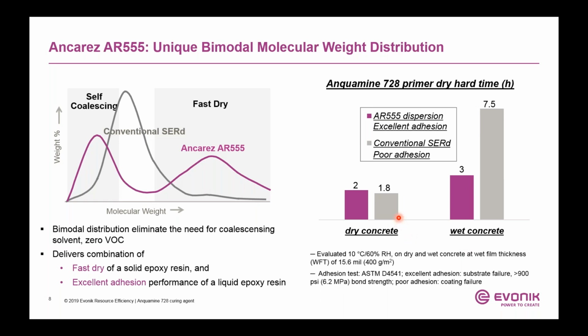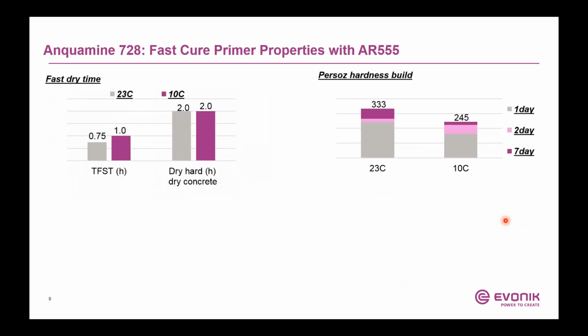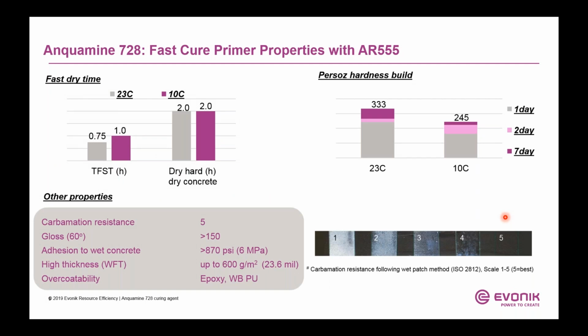And if we look at a conventional solid resin dispersion on dry concrete, it dries very fast, within 2 hours. But the adhesion is rather poor, so it doesn't quite stick to the substrate. And on wet concrete, the dry time is not only much longer, but the adhesion is also rather poor. So this slide shows that Anquamine 728 primer has very fast cure speed and good adhesion to concrete substrate. And what about the other properties of this primer? So we just represent some of the data.